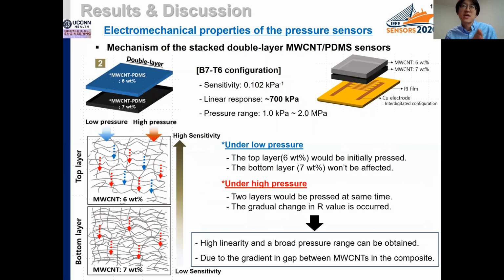On the other hand, in the case of the B7 T6 double layer sensor, the top layer would be pressed initially, but the bottom layer would not be affected at low pressures. At high pressures, both the top and bottom layers would be pressed at the same time, which leads to a gradual change in resistance like the schematic figures. So as our results show, if you consider the gap or resistance gradients of the stacked double layer composite films, we could obtain higher linear sensitivity and a broader pressure range.